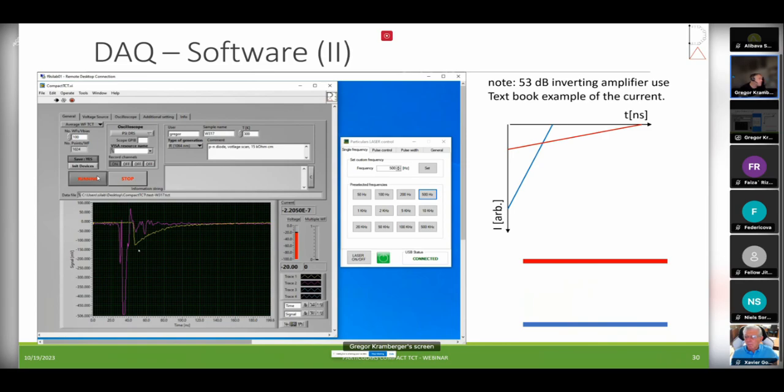Again, you will be able to see basically the textbook example of how the induced current looks like in a silicon diode. At minus 10, it's not depleted. You get this long tail. And then at 20, you still may not see that it's fully depleted. But at 30, you'll already see that this ends. And you have this linear part here, and the other linear part is here. So you see this nice textbook example of how the current should look like for the infrared. It's really like a textbook.